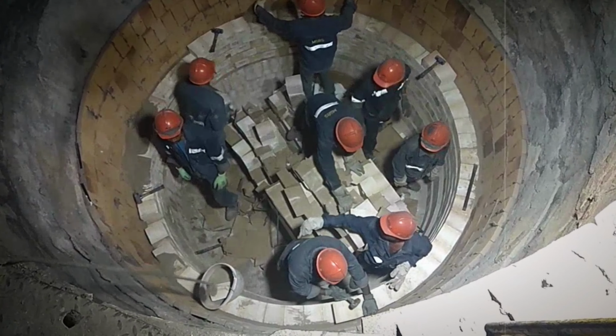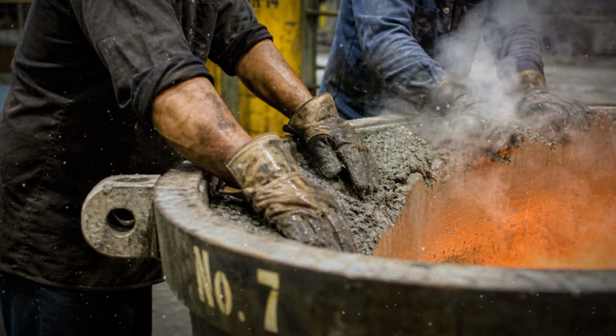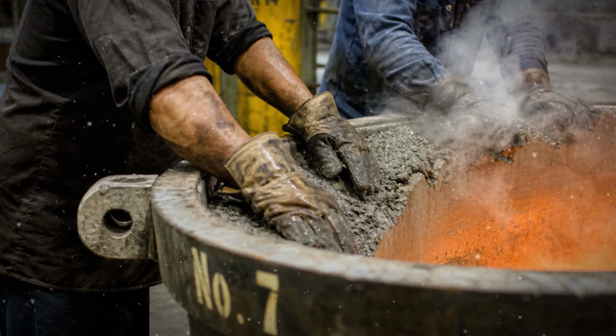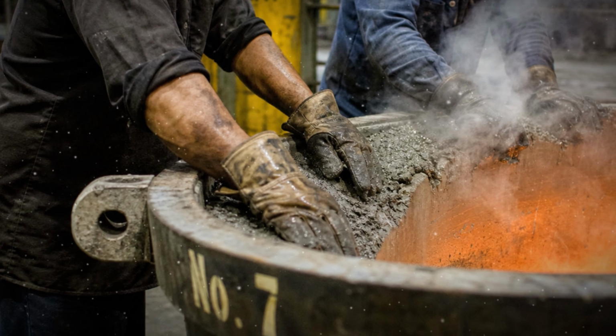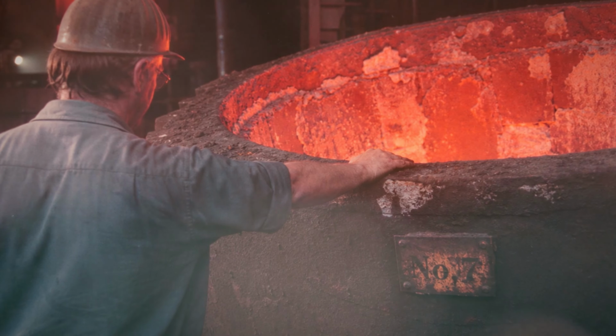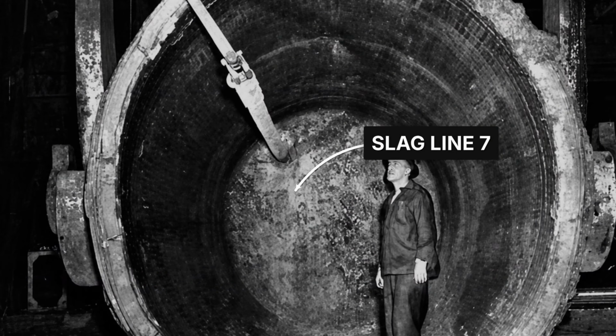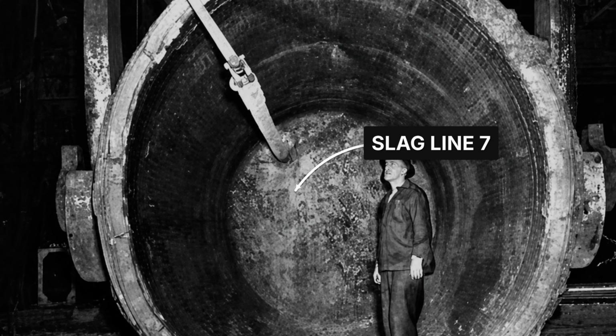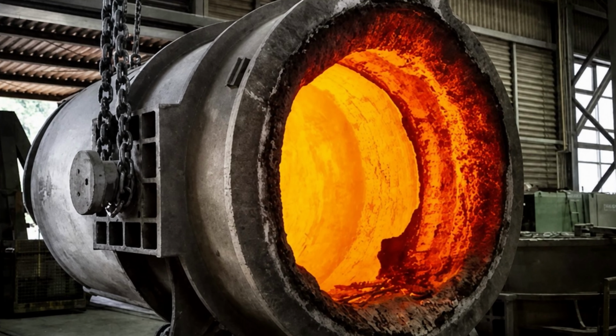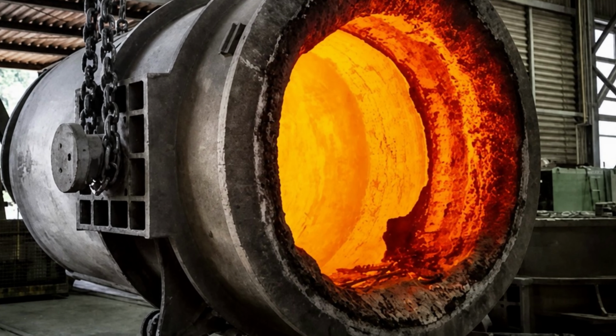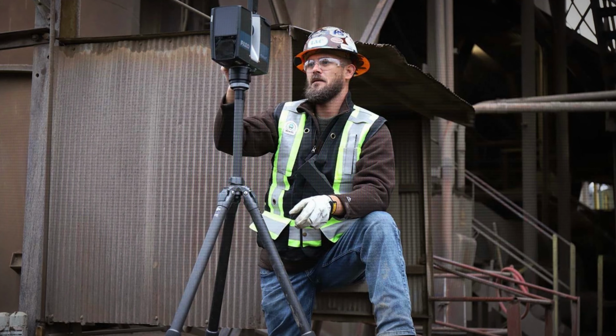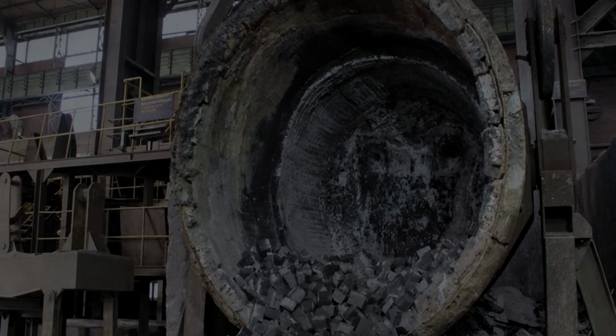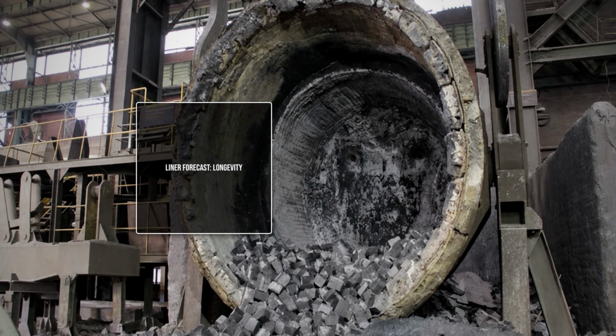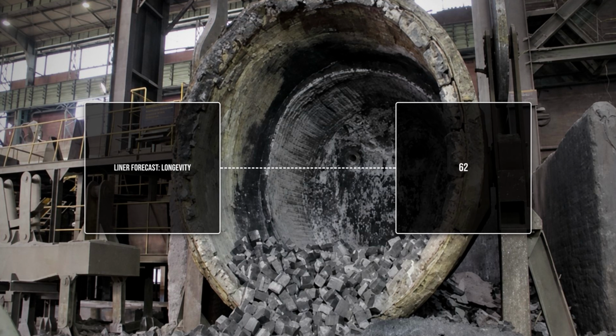The men who patched ladles worked inside them while they were still hot enough to bake bread, slapping wet dolomite onto the walls, and they knew each ladle by name and personality. Number 7 always washed out at the slag line. Number 12 had a soft spot near the nozzle. Laser scanners map refractory thickness today, precise to the millimeter. They still cannot tell you what the old liner could, not how thick the brick is, but how long it will hold.